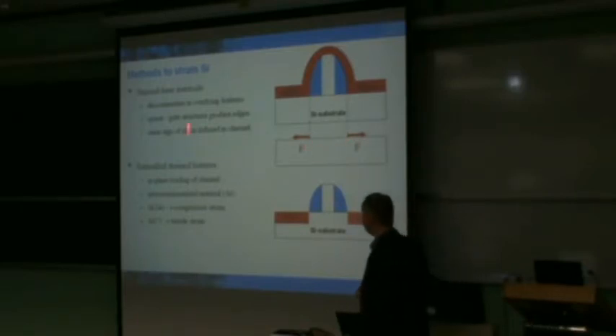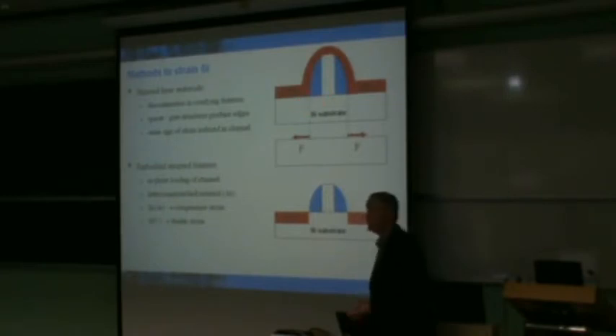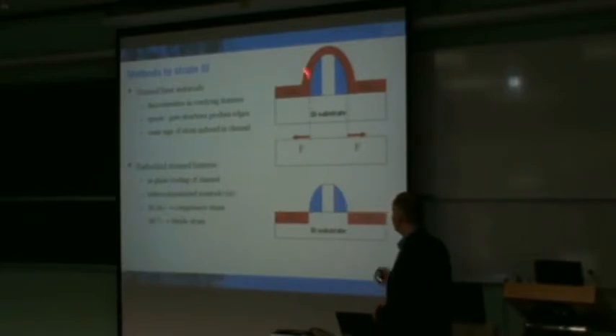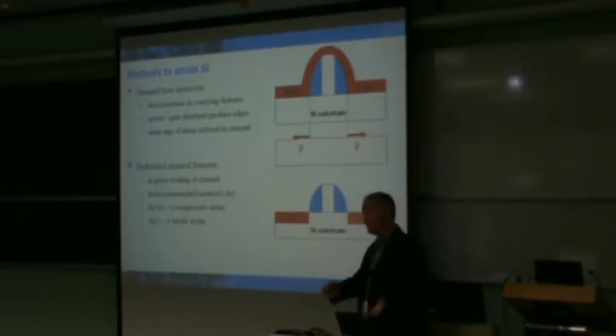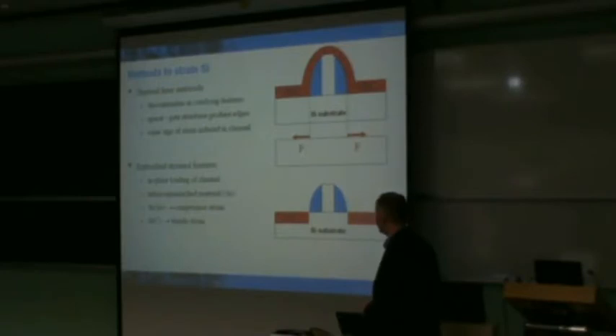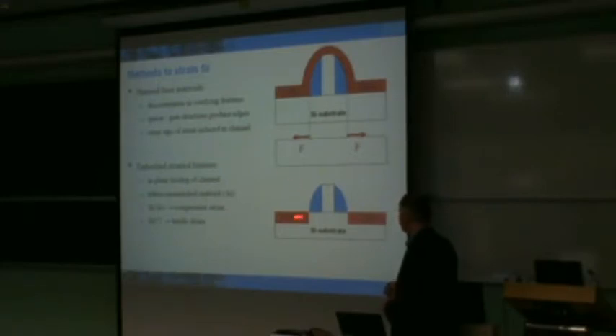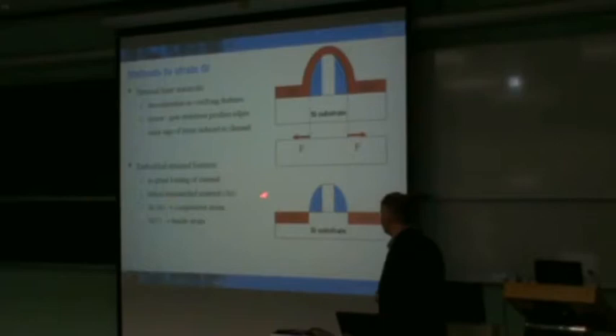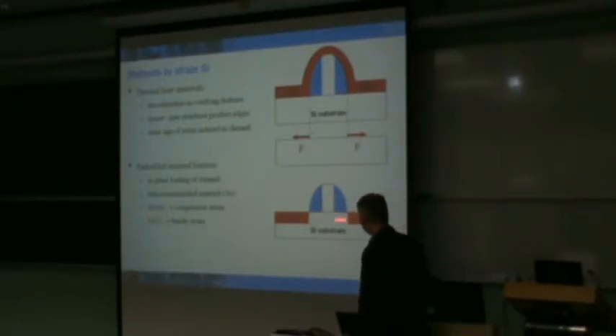And the key aspect here is that you can see that if you have a compressive film here, that will induce in-plane tension underneath, but it will induce compression in the region of the channel. And so you have the same sign of strain within your film as you do in your channel, and so you can easily engineer a material that will be compressive or tensile to accomplish that. The second way is the way that I showed also in the PFET example, in which you can use this embedded stressor structure, in which you have in-plane loading of the channel as opposed to something that comes from an overlying structure. And so you can use silicon germanium for the case of wanting to incorporate in-plane compressive strain here within the channel region.